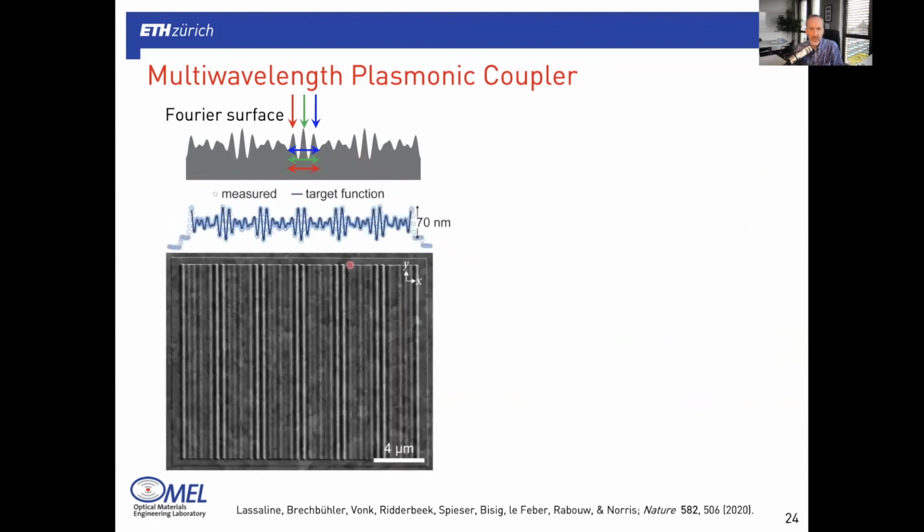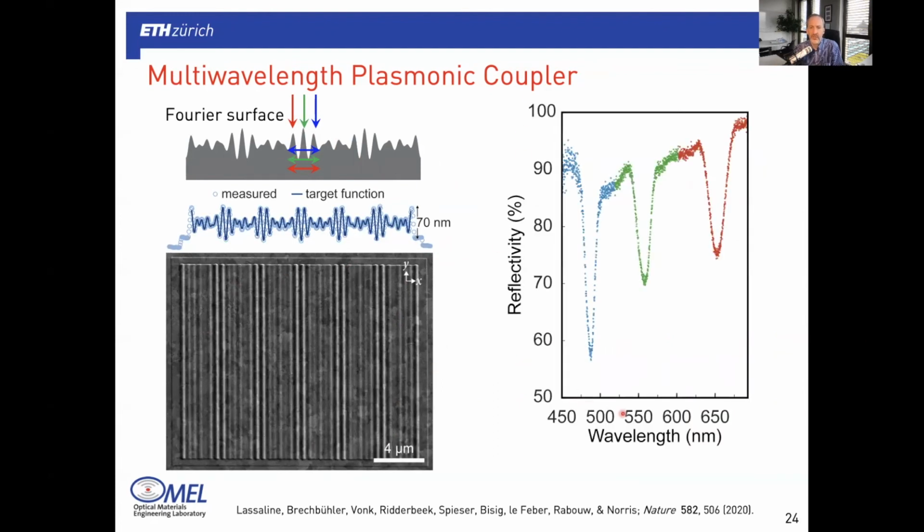Now, just to try to use this power to solve a problem, I mentioned that it is important to be able to couple, let's say, 3 colors of light into a waveguide mode, all at the same angle of incidence, in this case, normal. And so he designed this where the surface mode, waveguide mode, was a surface plasmon polariton. Here is the particular structure that Nolan designed and fabricated. And then here is his reflectivity spectrum, so reflection percentage as a function of wavelength. And here are the 3 design wavelengths that indeed are showing dips, photons not coming back because they're coupling into surface plasmons.